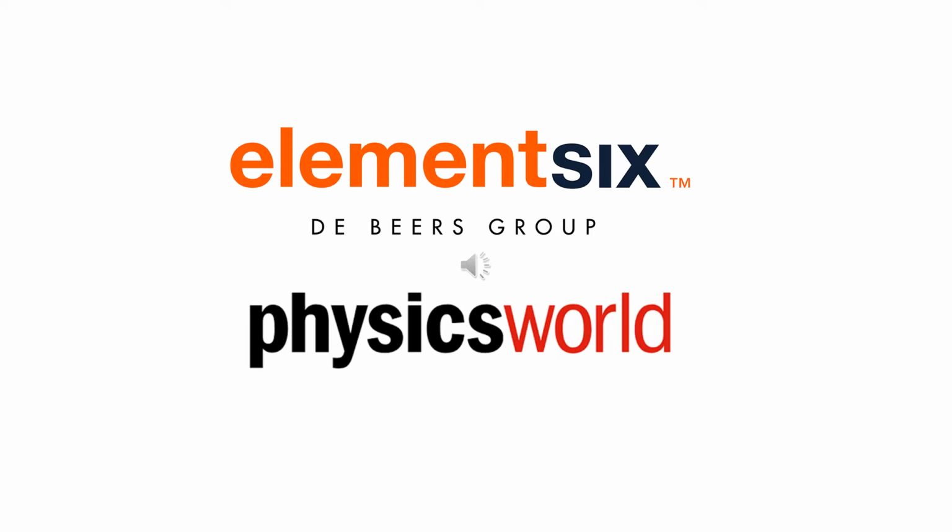So people refer to it as spin polarization, optical spin polarization: shining light on to manipulate the spins into this ground state. Now, normally with many other quantum systems, you get all your electrons into that ground state by paying the price of thermal energy. You basically have to cool them down to very low temperatures. Diamond, and this nitrogen vacancy center in diamond, is, as far as I know, still unique in the solid state physics community, in that you can spin polarize at room temperature and get those electrons into that ground state.